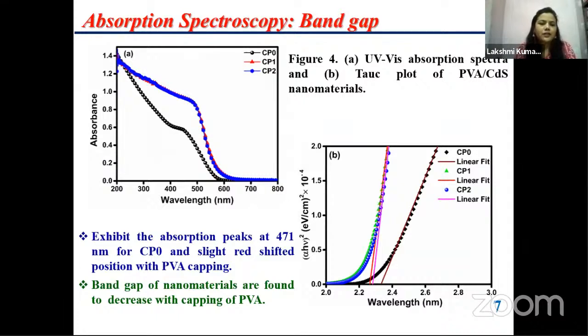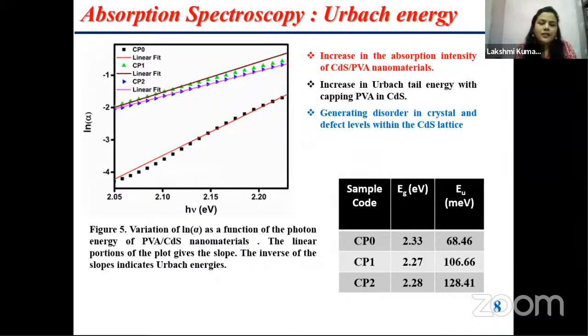After that, we have studied its optical property by absorption spectroscopy. From the absorption spectra, we can see for the pure sample the absorption peak at 471, and after capping with PVA, the absorption spectrum is slightly shifted and gains more enhanced visible absorption. And we have also plotted the Tauc plot, and from this we get that the band gap of the nanomaterials is found to decrease with capping, and it varies from 2.27 to 2.33, which I have mentioned in the next slide.